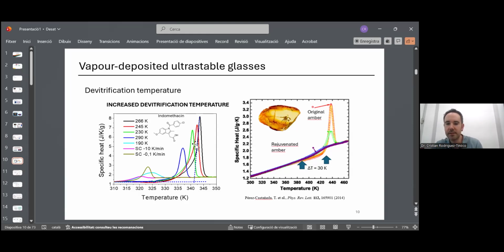And this very stable glass can be compared with, for example, amber, to have an idea of how stable this glass is. This was measured by Michelangelo Ramos, by the way, with amber. We see this change between the rejuvenated amber, which would be like the ordinary glass prepared by cooling from the liquid, and the original amber, which is a system that has been aged for millions of years. So we see a change in onset of the devitrification of 30 Kelvin, which is similar to this. Here we have like a 20 Kelvin difference in the devitrification temperature.